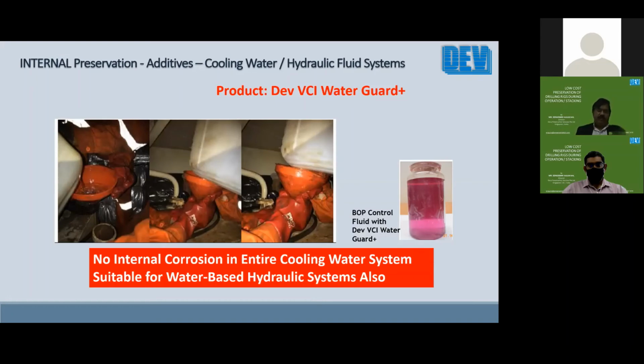Okay, and I'm happy to say that even after about 2.5 to 3 years of the monitoring, we have found that all the additives are performing as predicted or as required, and they have not caused any contamination of the fluids, whether it's a cooling water system or a lube oil system or a hydraulic oil system or a hydraulic fluid system. None of them have caused any contamination or a reaction, and they are performing as planned.